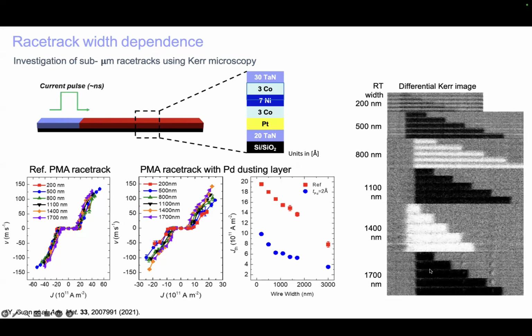We create a current pulse into the racetrack. The domain wall moves to the right. You can see, each time we inject a current, we take a picture and we can see the domain wall moving. So each of these sequences of images shows a racetrack with dimensions varying